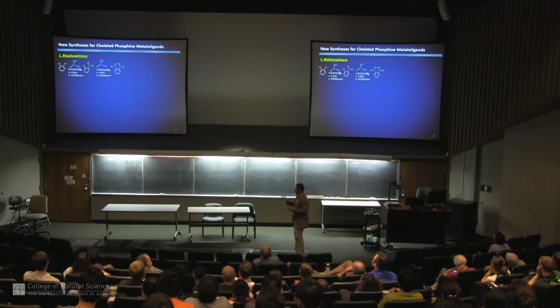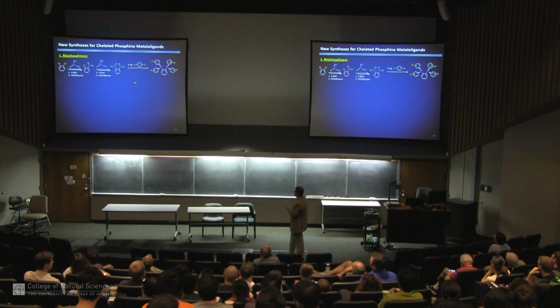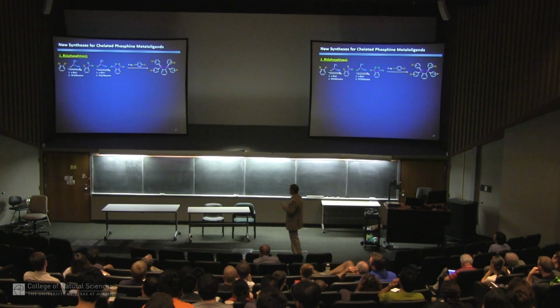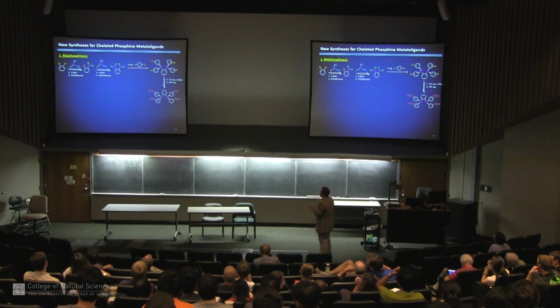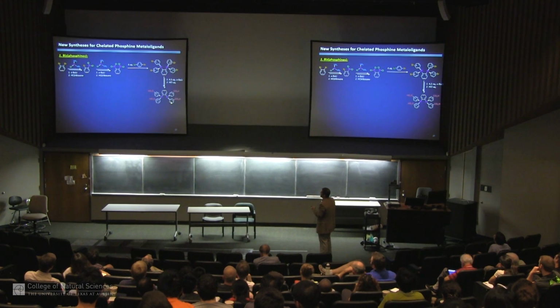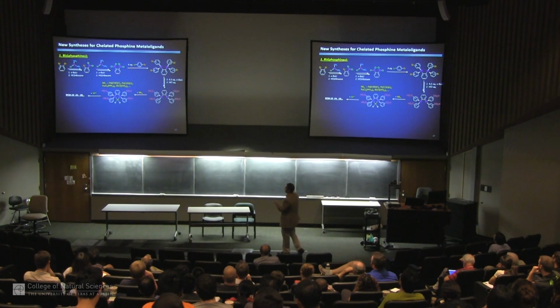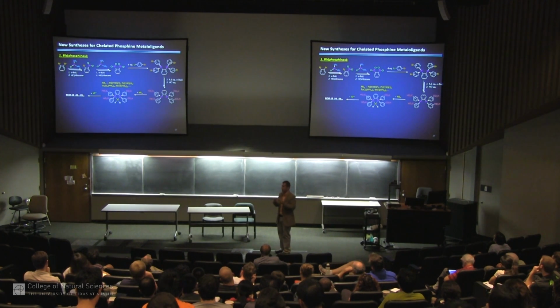And so the first time we did this is work that Alicia Bonzak managed to make work pretty well, is doing some organic chemistry to make these bisphosphine ligands. Without going through the organic chemistry in detail, this is pretty arduous, and there's several steps just to get to these precursors. Once we can get to this precursor, we can apply our same chemistry of lithiation, and we can make materials like this. Now, this looks like a ligand, to all intents and purposes, that many people have used in organic chemistry and in organometallic chemistry, but we've got our acid groups in the ancillary positions. So we can coordinate now a range of metals, and because this is chelating, it's a stable precursor building block.